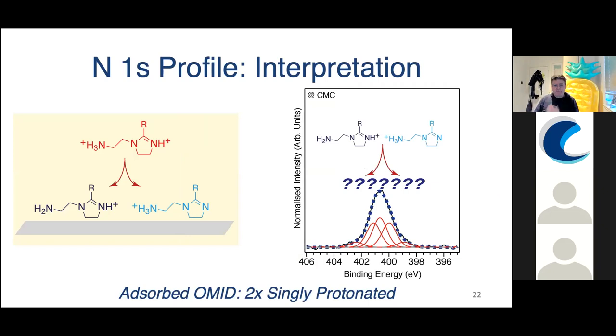So that helps us interpret the nitrogen 1s profile. Before I go into details of explaining how we interpret it, I'm just going to give you the answer because that makes things easier. What we believe is this molecule is going down onto the surface, on the basis of the nitrogen 1s signal, and forming two singly protonated species: one where the imine nitrogen is protonated, and that's the primary species, and this lighter blue one where the primary amine is protonated, which is the minority species on the surface. So there are two singly protonated species on the surface.